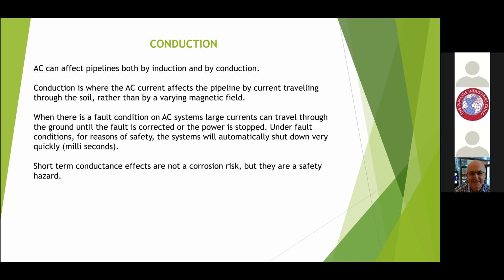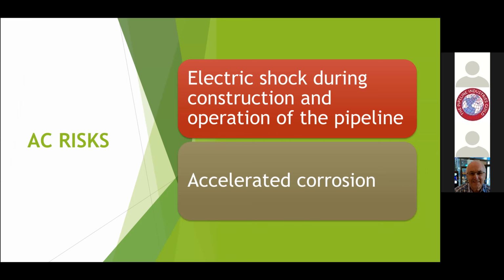But also, if there is a fault on the AC system that's powering the train, what they commonly call a ground fault, for a short period of time some of that AC current will also travel through the ground. Literally, it will travel through the ground. So the pipeline can be affected by that, but for a very short period. And we'll talk a little bit about the periods of fault systems. But generally, short-term conductance effects are not a corrosion risk. That's not universally true, but it's generally true. And we're going to consider firstly the risks of induced voltages and accelerated corrosion.